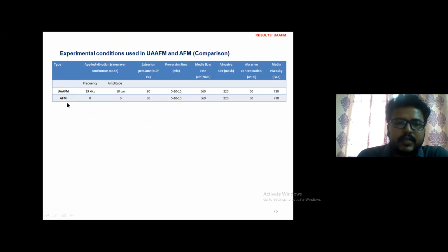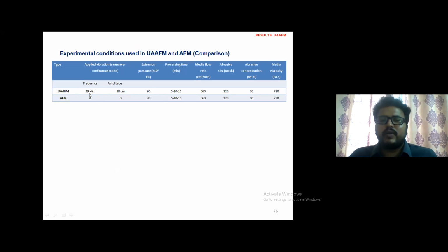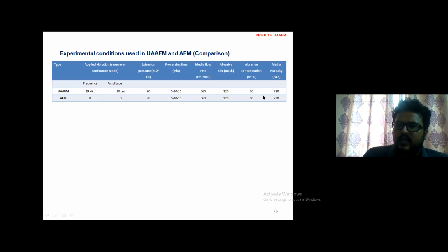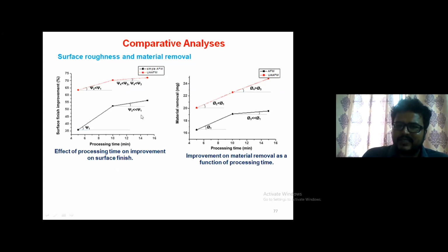One interesting study we have made is with simple AFM with zero frequency, and UAFM with 19 kilohertz frequency, and amplitude 10, which is constant. The remaining parameters are similar for UAFM and AFM. The only thing is we are giving the frequency in one case, and in the other case we are not. The remaining important parameters such as processing time, media flow rate, abrasive size, concentration, and media viscosity are kept constant. Our main research is to minimize the processing time, right? We achieved that by applying vibrations to the workpiece.